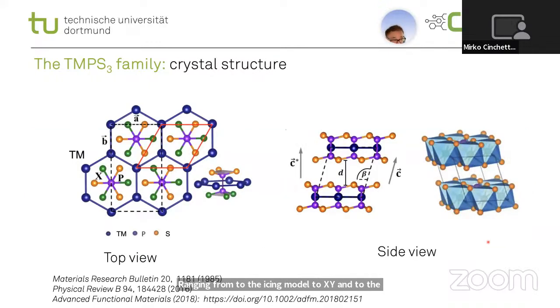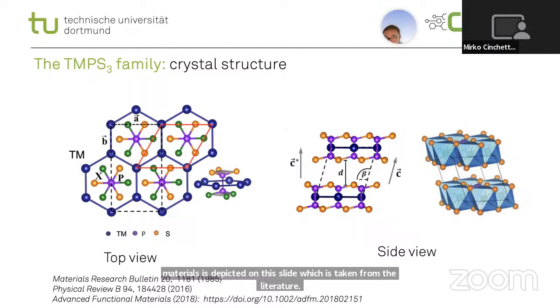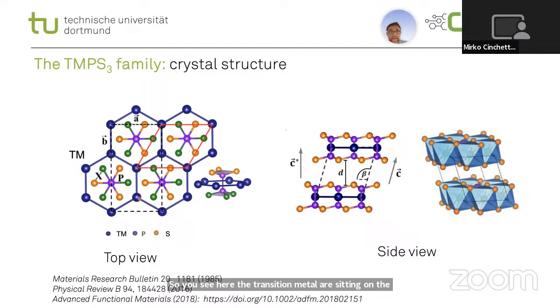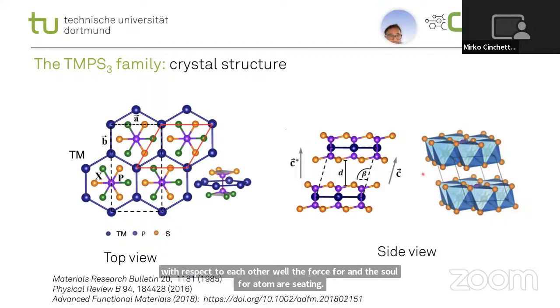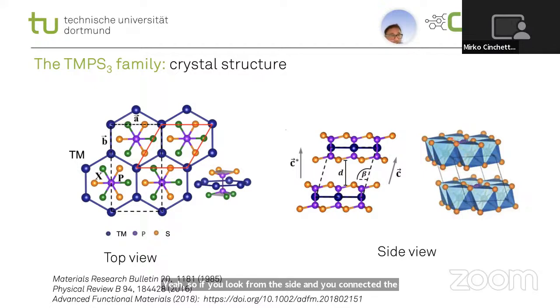The crystal structure of the materials is depicted on this slide, which is taken from the literature. So you see here the transition metals are sitting on a hexagonal lattice, and then on the top and the bottom of this hexagon, there are these pyramids, which are tilted with respect to each other, where the phosphorus and the sulfur atoms are sitting. So if you look from the side and you connect the phosphorus and sulfur atoms, you obtain this octahedron, where in the middle you have your transition metal. And this configuration will become important in a while.